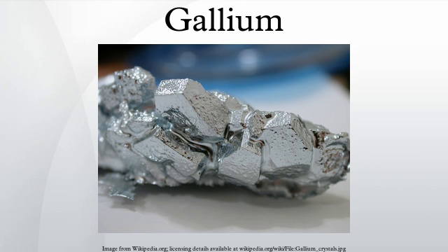Galinstan and other alloys. Gallium readily alloys with most metals, and has been used as a component in low-melting alloys. A nearly eutectic alloy of gallium, indium, and tin is a room-temperature liquid that is available in medical thermometers. This alloy, with the trade name Galinstan, has a low freezing point of negative 19 degrees Celsius. It has been suggested that this family of alloys could also be used to cool computer chips in place of water. Gallium alloys have been evaluated as substitutes for mercury dental amalgams, but these materials have yet to see wide